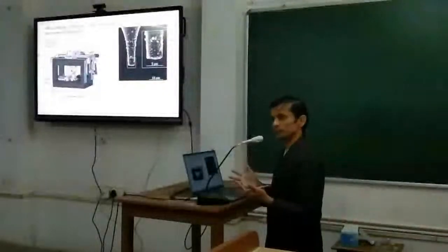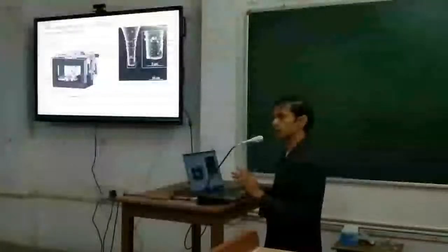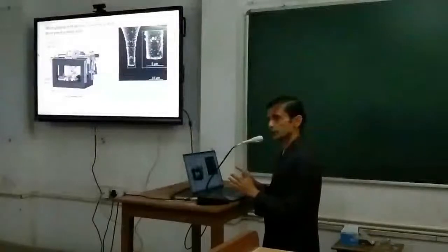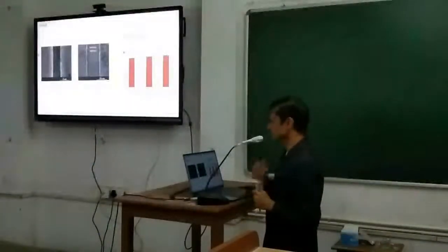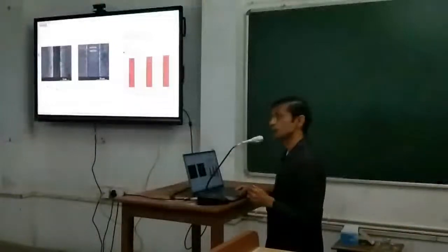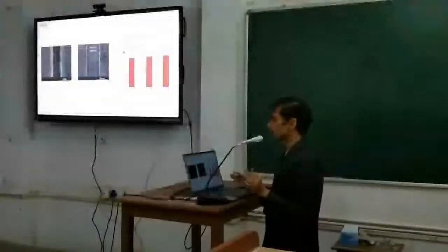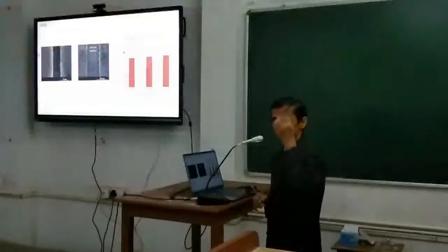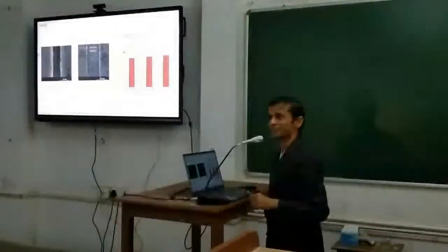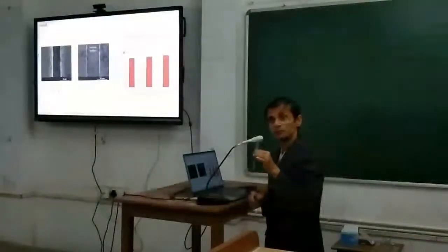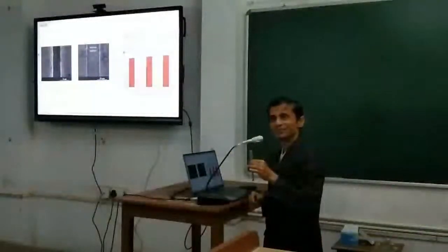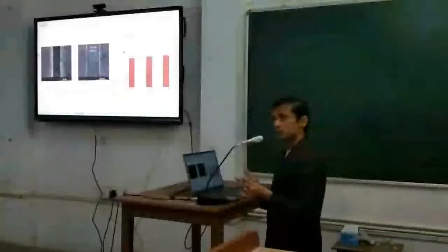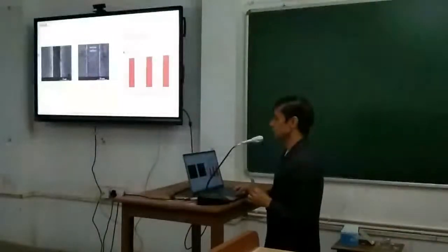In one center you have everything, and the structure is also very different with respect to the normal machining center, because this kind of machine tool can offer very high rigidity. It's very high precision. These are the micro tools, micro grooves with a tool diameter of 4 micron. So a 4 micron tool, you cannot just make it on a different platform, take it here, put it and grind. Just imagine 4 micron. How much is the micron level diameter of your hair? So it is a 4 micron tool, but it's a rigid tool because it's a solid carbide. And with that you have to machine. Why you need a rigid tool, that also will come. So finally, you can see that it is machining micro grooves quite effectively.